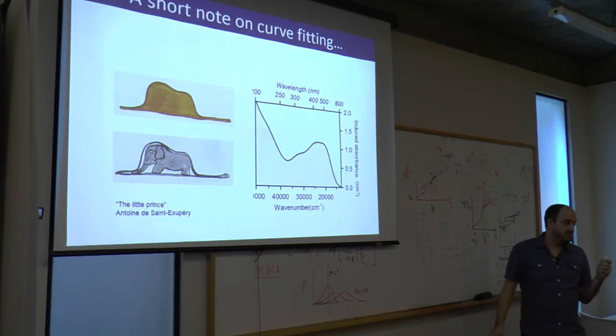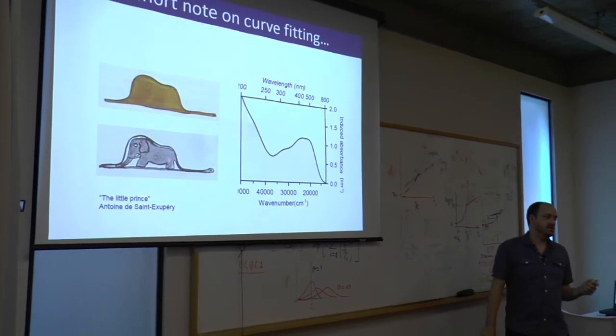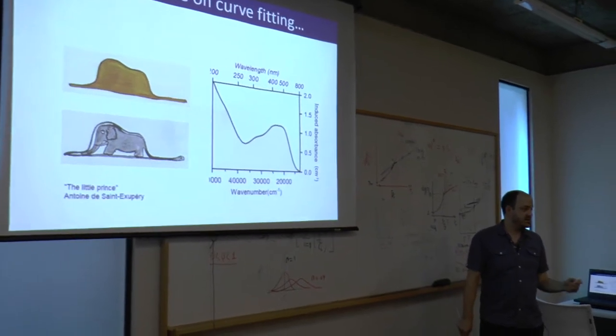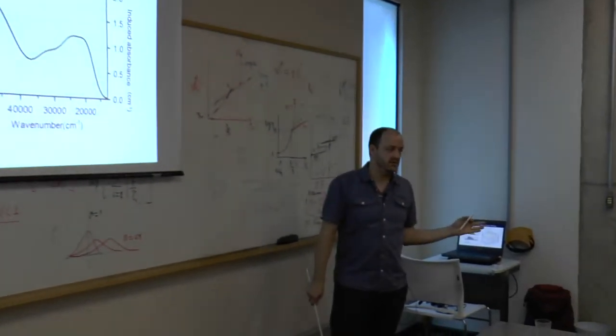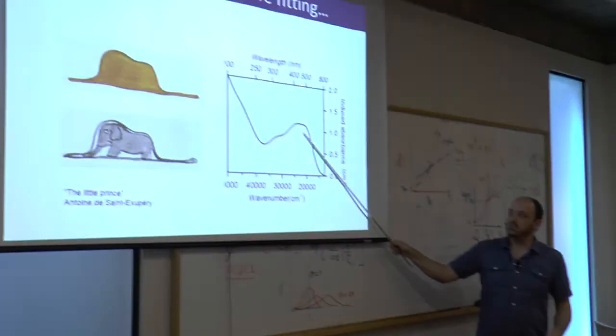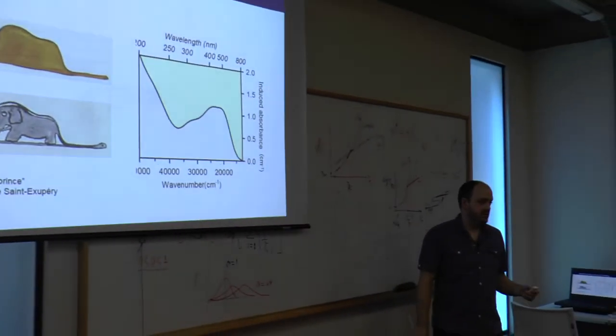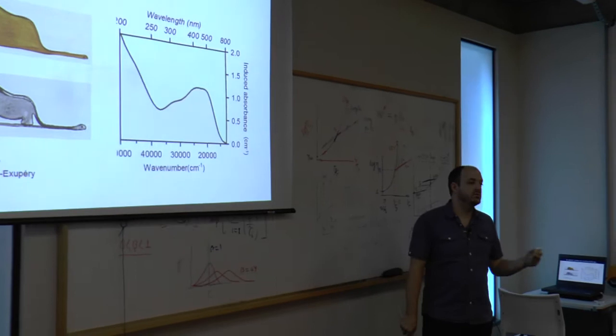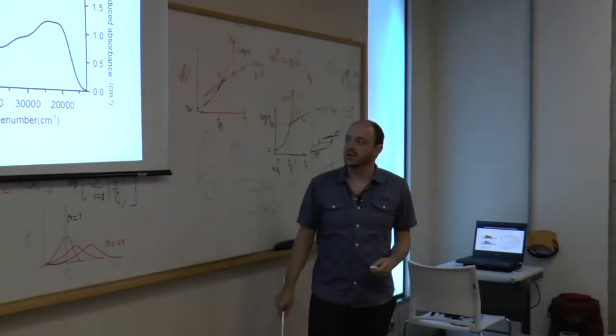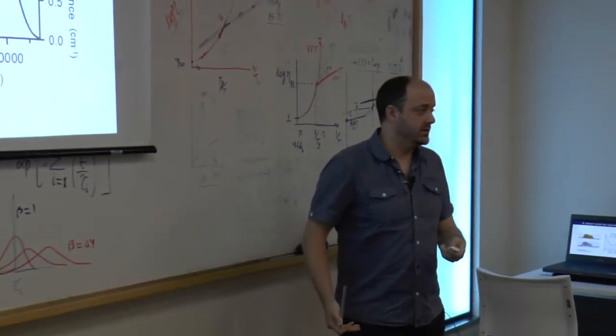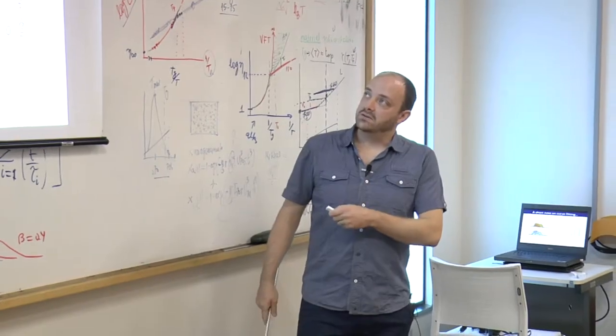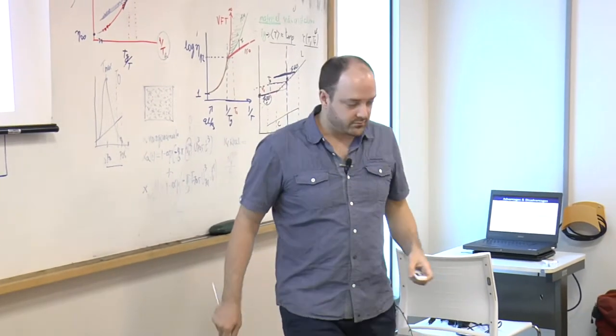So bottom line is, when you put a peak in, you should find an assignment. And even if that is just saying what other people have made for this assignment, but know what you're actually putting under these curves. Have an idea of what structural unit it is and what you would expect based on how you're modifying your composition or your experiment. So that's my short note.